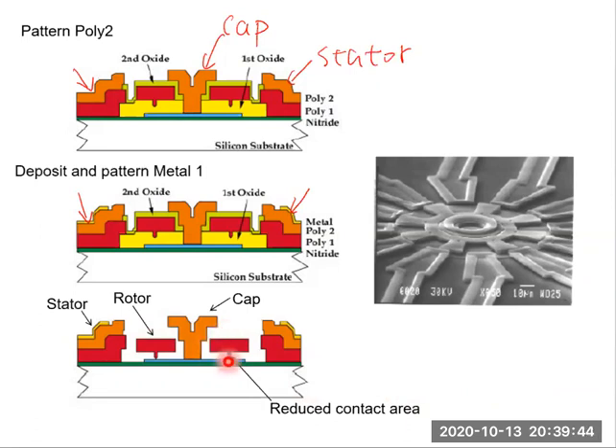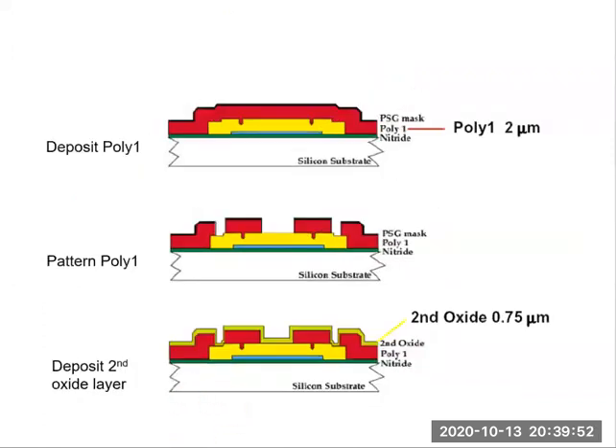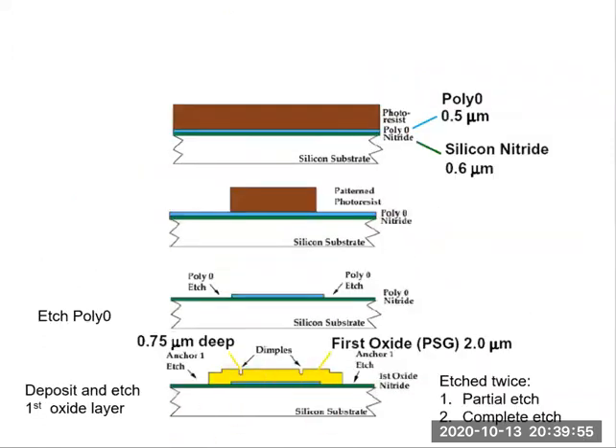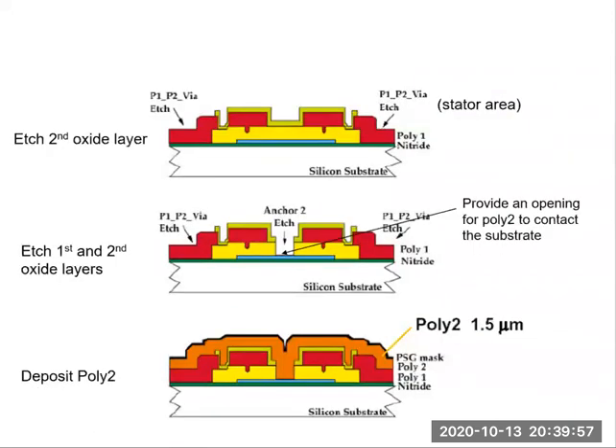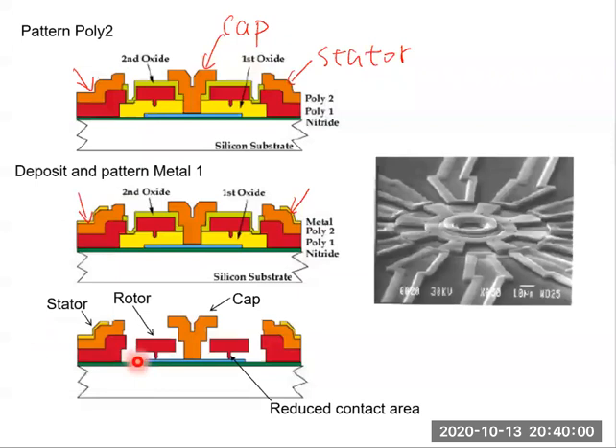I know that due to the dimples etched in oxide 1, the first oxide layer, we etch the dimples in this step. Now we can see the purpose of these dimples. Right, due to these dimples, the contact area between the rotor and the substrate is reduced. So this dimple structure helps reduce the contact area and reduce the friction.